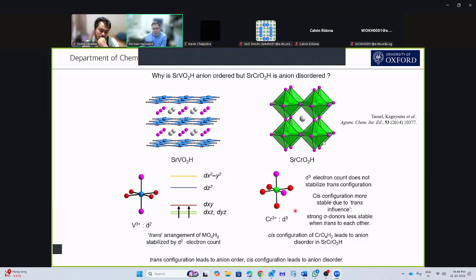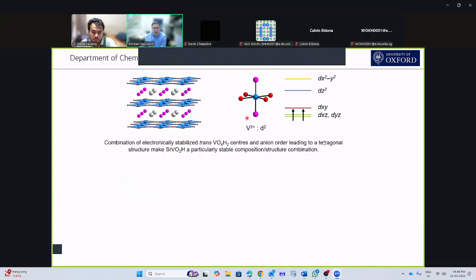And we can justify this on the basis that the 2 hydride ions are the strongest sigma donors in this system, and we have something called the trans influence, which tells us that 2 strong sigma donors shouldn't be trans to each other. So normally 2 hydrides would be cis unless we have this electronic stabilization. And this electronic stabilization means that the 2 hydride ions are trans, and then we can get oxide hydride order, and now I can shrink this distance because a hydride ion is more stable than an oxide ion.